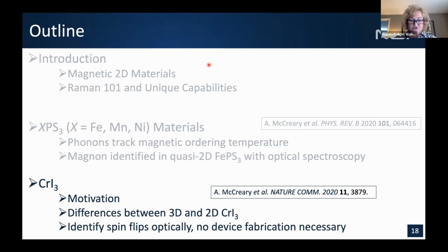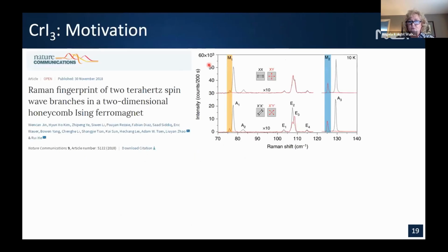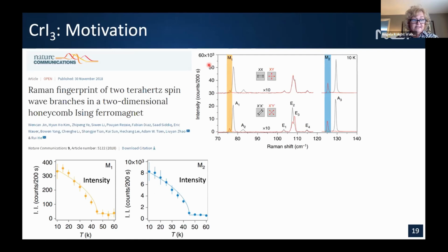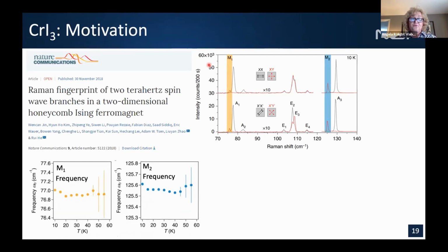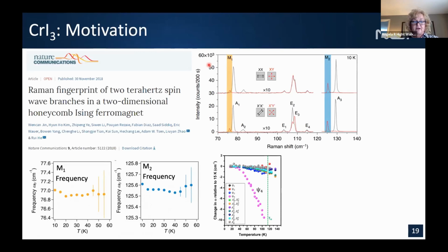And this paper just went online this week in Nature Communications. So I'd like to motivate why we looked at chromium triiodide, because everyone and their friends are looking at chromium triiodide. So it wasn't clear that we could add anything new until, as we were finishing up our iron PS3 work, this paper came out where they identified two possible magnons in the chromium triiodide. What was interesting when we looked at their data was not the intensity, but the frequency versus temperature. Remember, ours had that dramatic drop off in our magnon in the iron PS3. They really kind of saw a consistent frequency with temperature. And so that made us wonder.